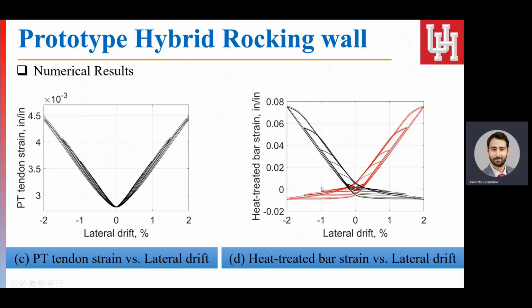And then lastly, we also plotted the heat-treated bar strain versus the lateral drift. So in general, based on our experience from the coupon test, we noticed that if the heat-treated bar strain remains below 0.1 or 10%, then we should be able to avoid strain localization and necking, which is essentially achieved in this case as the bar strain remained below 0.08.